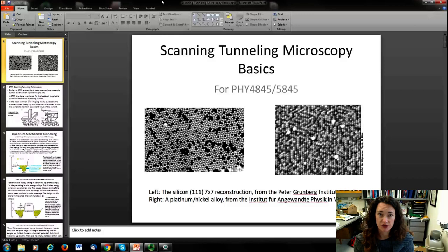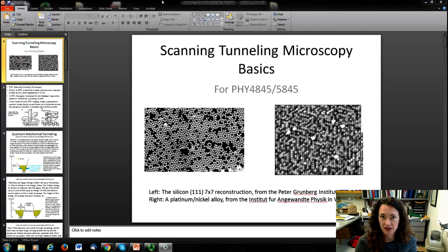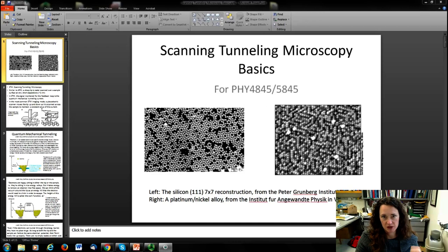For example, lots of times in atomic force microscopy you can see the periodicity of the lattice pretty easily, but it's difficult to get true atomic resolution. How do you know that you've got true atomic resolution? Well, you can see point defects and differences between the sample atom to atom, instead of just seeing the regular array of the lattice itself, which is what you often get with atomic force microscopy. For an example of that, look no further than the two images in front of you. The silicon 7x7 reconstruction is pictured here on the left. The 7x7 reconstruction is a specific phase that the silicon material will go into once it passes a temperature threshold. You can see that the atoms are pictured as these bright circles — basically little balls — and you can see vacancies within the lattice and defects. So you know you're getting true atomic resolution.